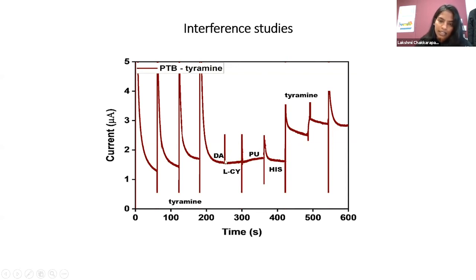So it means this analyte doesn't have interference towards the detection of tyramine. And then again, we added the tyramine, three additions. So it means this electrode has a high selectivity to detect tyramine, because we don't see any interference effect in this study. So that's why we feel this polymer electrode has good sensitivity and also selectivity.